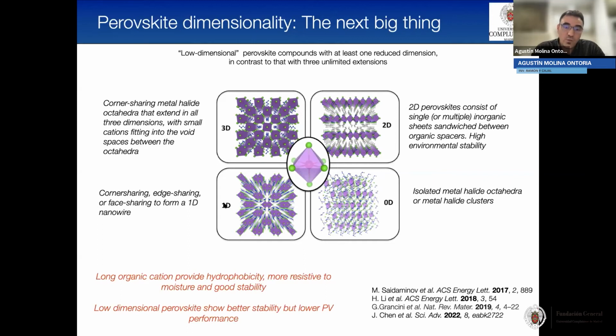Also, we can have 1D perovskites, or perovskitoids, that are corner sharing, edge sharing, and face sharing to form nanowires. And on the other hand, we can have 0D perovskites or perovskitoids that are isolated metal halide octahedra, or can be considered as clusters. Introducing these long organic cations provides hydrophobicity to the perovskite, and therefore it is more resistant to moisture, and they are showing better environmental stability.